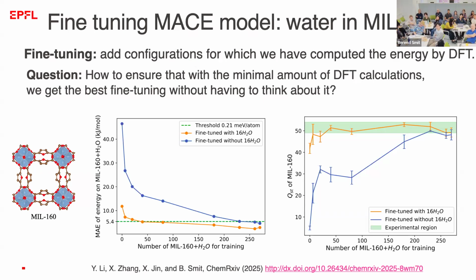And so what we try to do here is take that MACE force field out of the box, and try to predict the heat of adsorption, which you can measure for water in the metal organic framework. It's in this MIL-160. So this is the value you get if you take it out of the box. And you see it's 10, experimentally it's 50. But this is a difficult calculation because you calculate the heat of adsorption by doing a simulation of water in the metal organic framework, and you do a simulation of the metal organic framework, and you need to subtract the two. So you have two large numbers. So the requirement for accuracy is typically much more than what you see in these leaderboards. But what you can see here is if we add training data where we fine-tune the model, we can get to the experimental value.